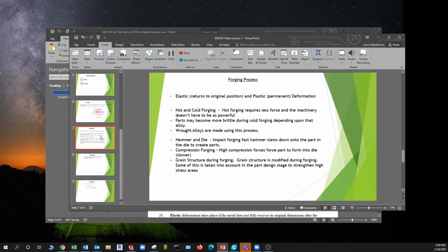So the last on the list is the one we heat up, beat on, heat up, beat on, heat up, beat on until it's in its final shape, and then we let it air cool. And that's the softest one. And then the next hardest one is the cold forged one, which we didn't give any heat at all. And the hardest one is the one we hot forged, but then we did one final step and we heat treated it. When we heat treated it, we were able to get it quenched to get a hard enough surface to where it would cut into the other wedges instead of being cut.